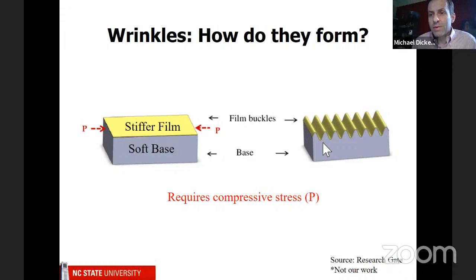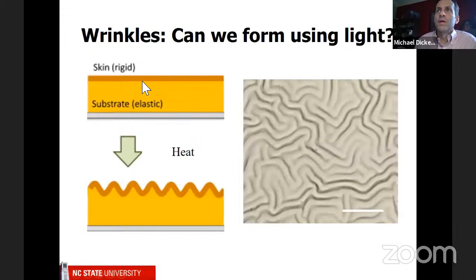All right, so turns out this is really easy to do. And if you just take, let's say, a glass slide or a silicon wafer and you put a polymer film on it and you coat it with a thin layer of a rigid material like gold, for example, and you heat it, well, those two materials have different thermal expansion coefficients, and that is enough to generate stress such that it will actually form these wrinkles. This is what they look like. They kind of look like spaghetti on the surface.